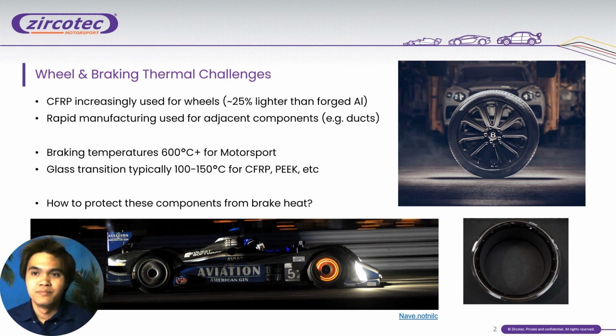Other parts inside the wheel assembly can be made out of plastic, either carbon fiber or 3D printed materials, such as PEEK and nylon being the popular ones. The bigger problem with these materials is that they must withstand braking temperatures. When you apply the brakes, friction is created between the brake pads and the brake discs and thus generates heat, and this heat dissipates to other parts within the wheel assembly.